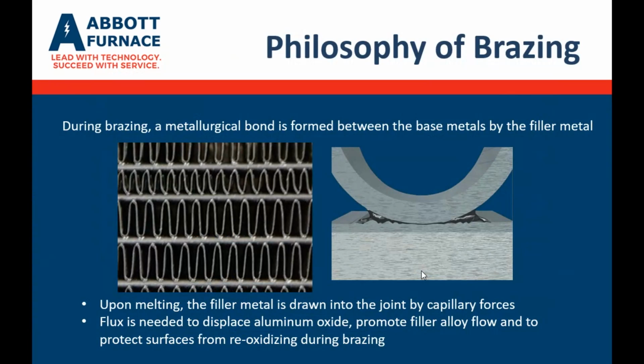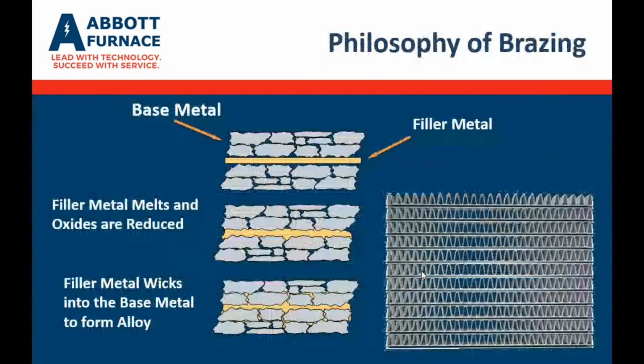Part of the process we're going to talk about too is the flux. What's the purpose of flux? How is it applied in this process? But the flux is needed to displace the aluminum oxide. Oxygen is a major enemy of what we're trying to do in the brazing inside of the furnace. So anything we can do to displace the oxygen is very helpful throughout the entire process. The flux also helps to promote filler alloy flow to get that liquid fillet into that joint to fully fill that gap. You have your base metal, and then we have your filler metal. So the process is to heat the filler metal up so it starts to melt and then wick into the base metal to form a very solid and strong joint.